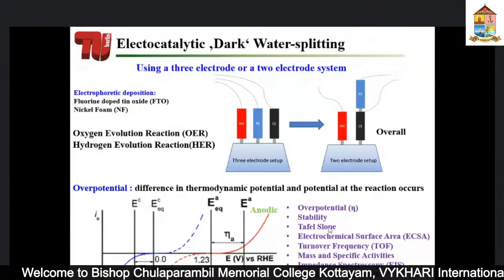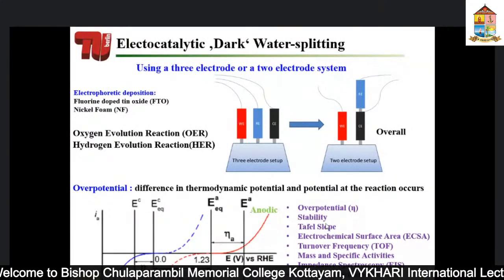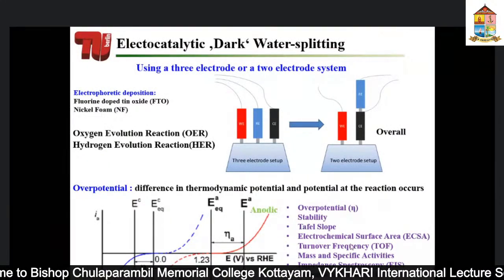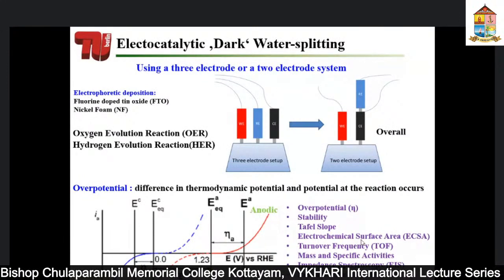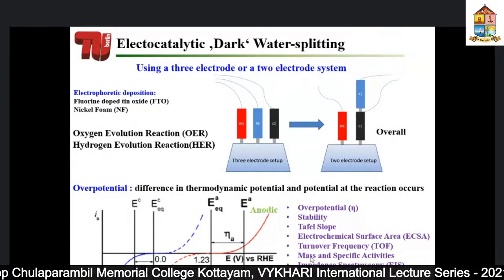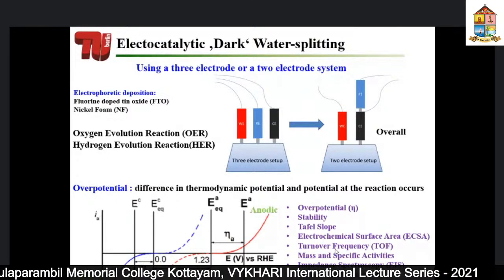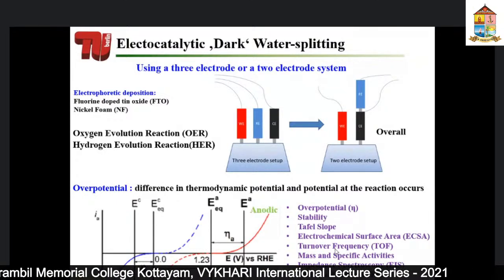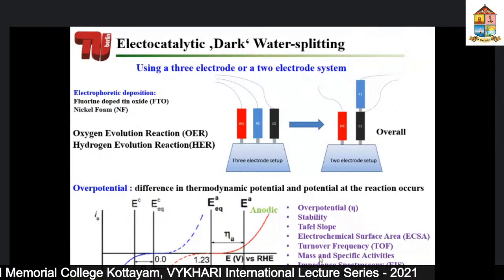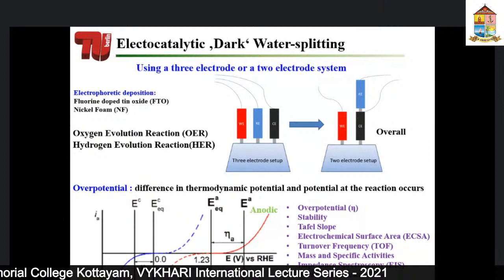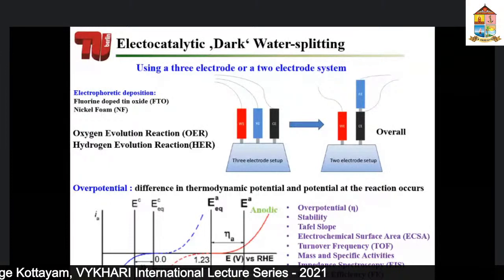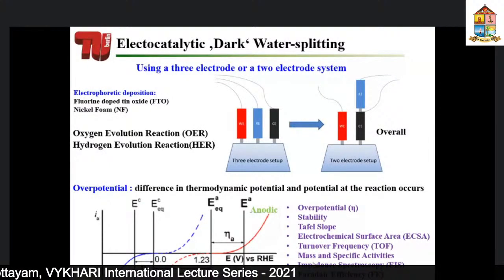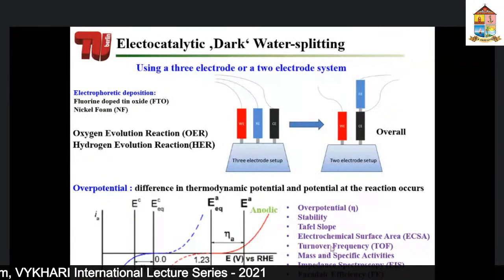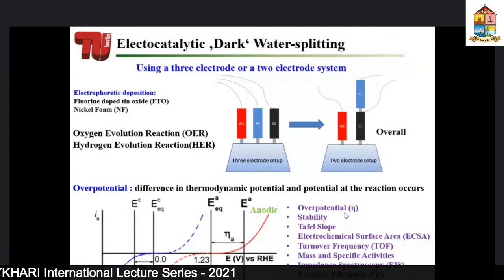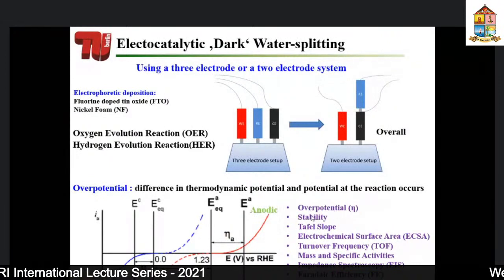of reaction. There are some other parameters which are also very important, such as Tafel slopes, which determine the kinetics. There are factors such as electrochemical surface area, how many active sites are available on the surface. You have turnover frequency, which will tell you how fast the reaction is, and then you have mass and specific activities: how much loading of the catalyst is required, and something about charge transfer, which is done by impedance spectroscopy, also Faraday efficiency, which determines how much oxygen and hydrogen you produce. I will not go into any of these details because they are probably not important at this point of time. What I will stick to is over-potential and stability, which are the fundamental and very important parameters to have such a reaction.